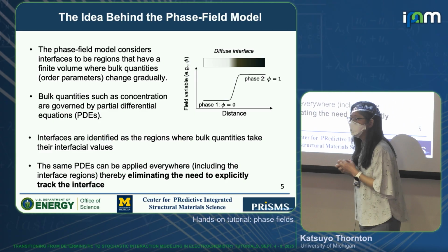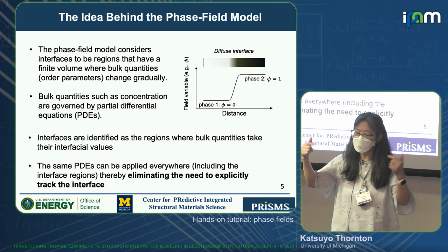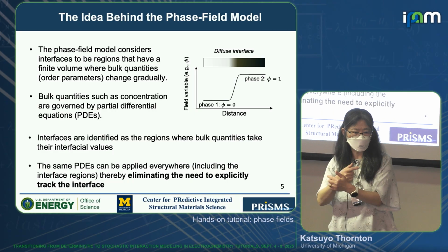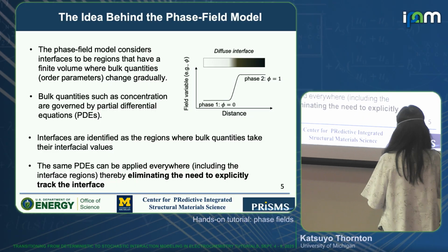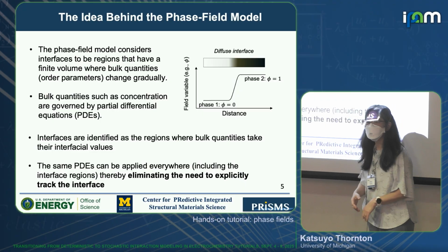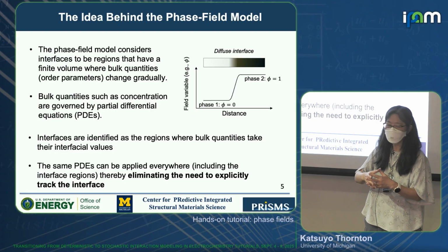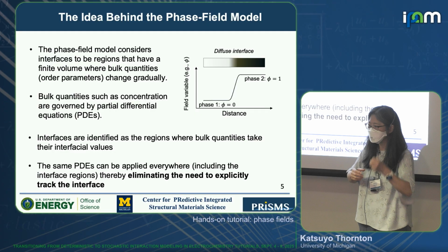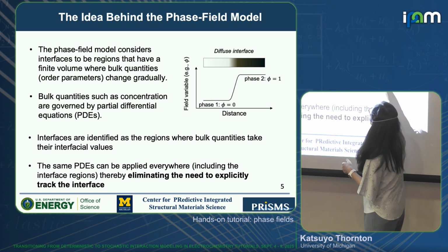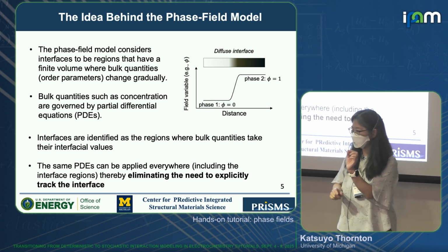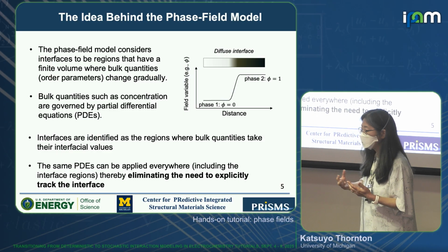These things are really hard to deal with if you have to keep track of a sharp interface, a mesh interface, because sometimes those mesh points can get tangled up as they overshoot and cross each other. The nice thing about a diffuse interface is that these things happen naturally. Pinching happens naturally, and when something disappears or is created, it's very well regularized because the diffuse interface gives a length scale by which the system is regularized.